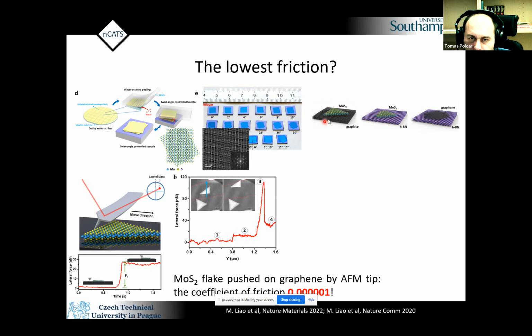Another way, as I said, is that we can load this flake here and drag it. If you do that, you can increase the load and get a coefficient of friction. That's what we get. And what we got was a friction of 1 millionth, I think the lowest ever measured. We were pretty excited by that, because it was 2 orders of magnitude lower than any other report we could find before.